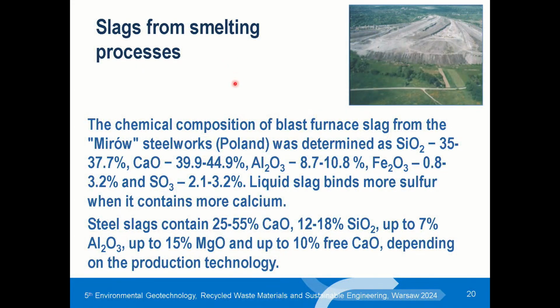The next is slag from smelting processes, and the exemplary blast furnace slag from one of the Polish steelworks. Its content is given on the slide. The content of steel slag is quite different, and you can see it below. Slag with lower content of free lime have pozzolanic properties, but high content of free lime allows use of slag as a hydraulic binder.